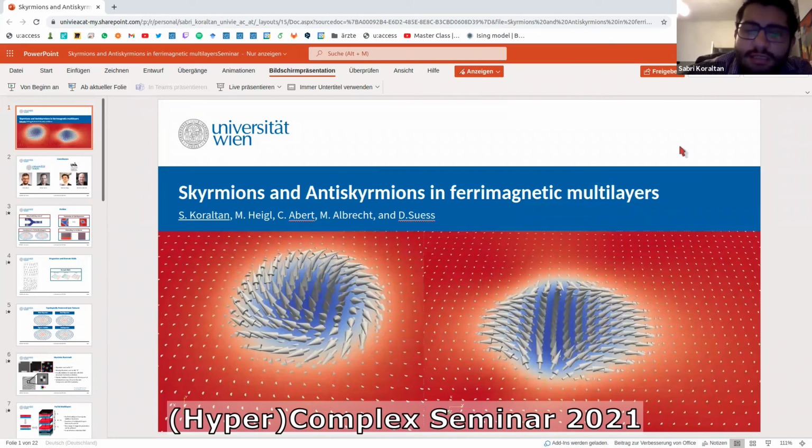If you have a regular nanowire with one skyrmion, you can apply a spin polarized current, and then you would be able to keep the skyrmion on the track and move it along the current. But with time, there is the so-called skyrmion Hall effect, where it would start to drift in one direction.